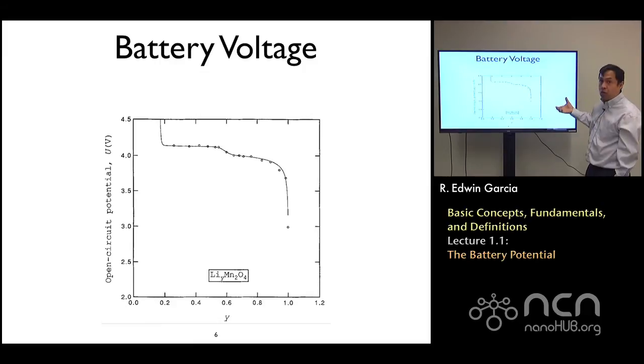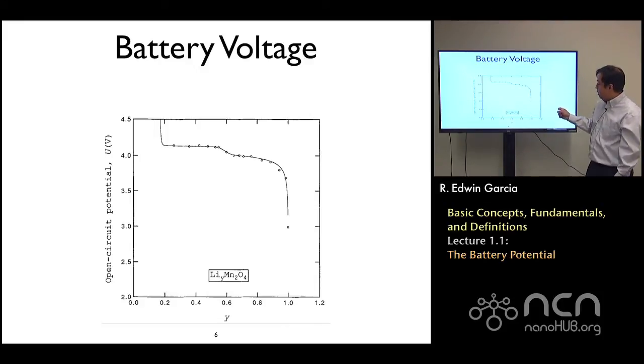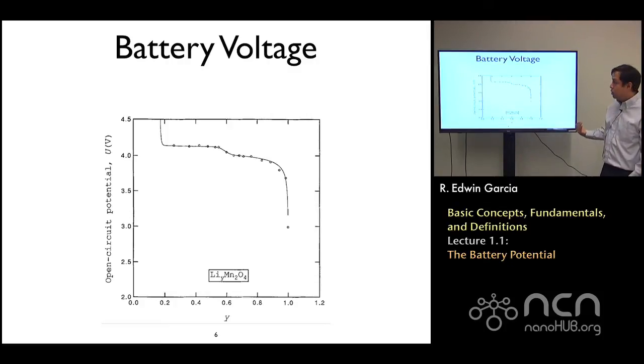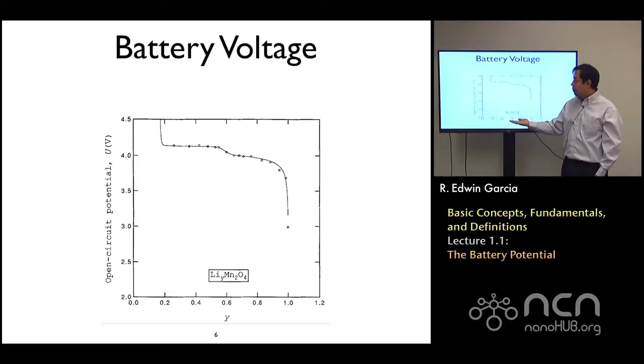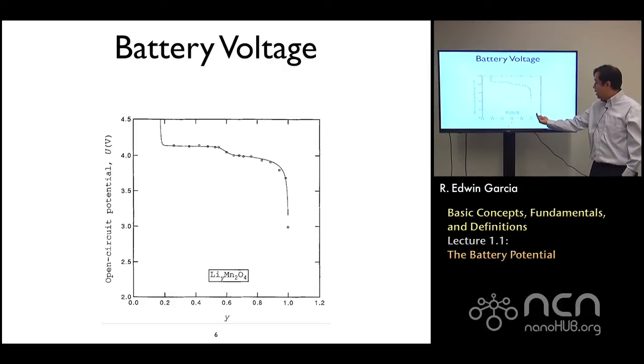and actually there is another lithiated phase that can also be used as a battery, and this is LiMnO2. But the reaction between the LiMn2O4 and LiMnO2 is such that this transformation could be non-reversible and induces a lot of stresses, so people typically focus either on this phase or on the low voltage phase. For the high voltage phase, the advantage is that we have a larger potential, and for the low voltage phase, what we may have is a plateau that makes it more stable.